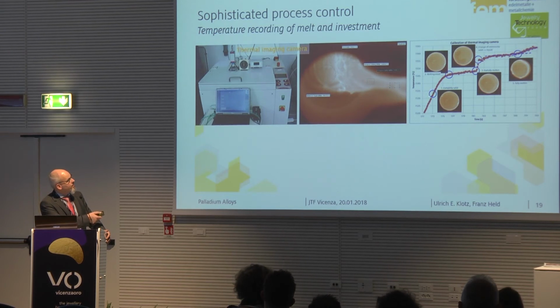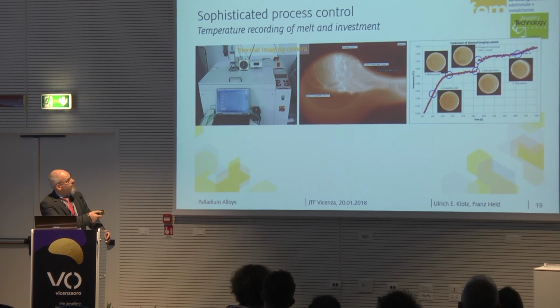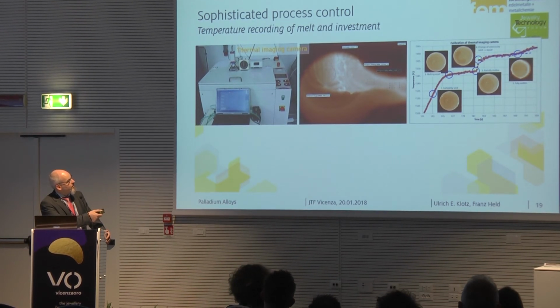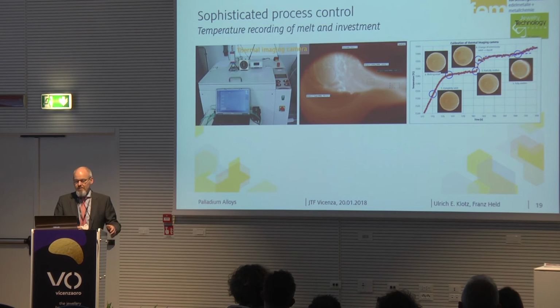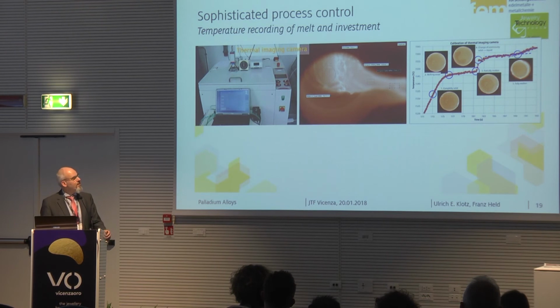So here everything is solid. Then melting starts. Then there is a jump here. This jump is a measurement effect. This happens during the melting process. And then we get the melting temperature, and then there is a kink here in this line, so it's more or less horizontal, and then it increases. So this is the point where melting is completed, and then you have to have a precise temperature control to cast at the right point.